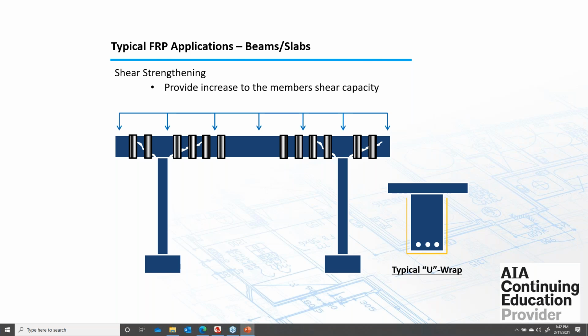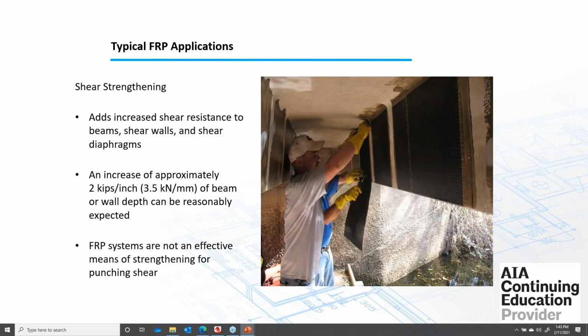But then there's instances where maybe there's a steel plate that's already been installed on the bottom, or you've got obstructions of some kind and you just can't wrap underneath and around. In that case, you actually can just put the material on the sides only, but you do get a further reduction in the capacity provided when you do that. But it is a possibility. So if you have an obstruction, don't just say, oh, I can't use FRP because I can't get a U wrap. That's not the case. It's just you get a reduction in capacity provided by the FRP. So again, similar to flexural, any type of concrete is fine.